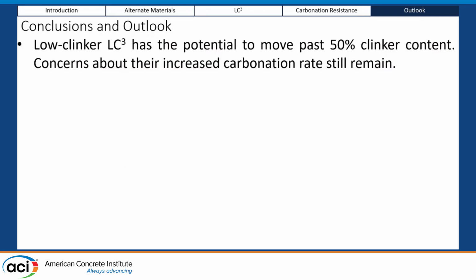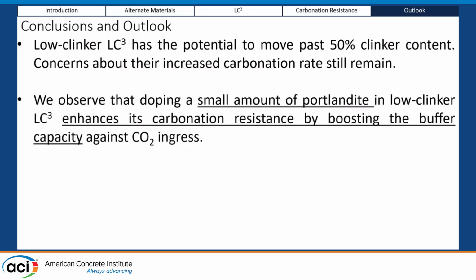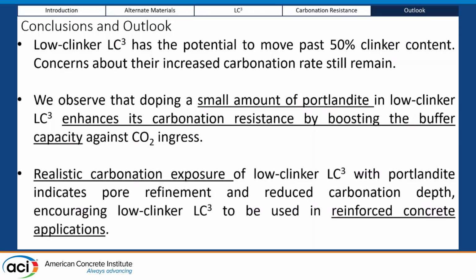So to conclude, we have shown that LC3-35 and lower clinker contents are possible, but we definitely have to look at carbonation resistance. Our solution involves adding a certain amount of portlandite to an LC3-35 system to enhance its buffer capacity in 2 ways. One is we enhance its buffer, and second, we also refine its microstructure so that we inhibit CO2 from ingressing with time. Finally, realistic carbonation exposures are important to consider with these low-clinker systems because accelerated carbonation might not be the most accurate way of depicting their carbonation resistance.